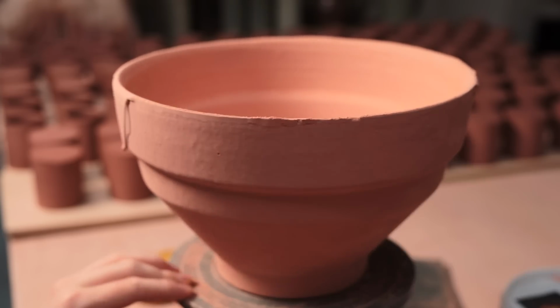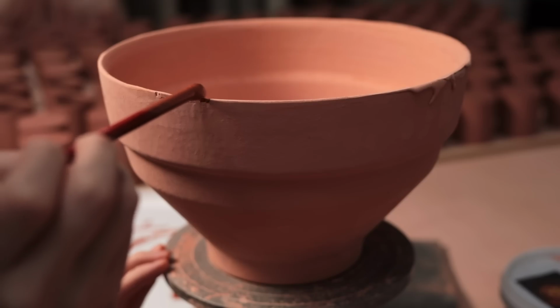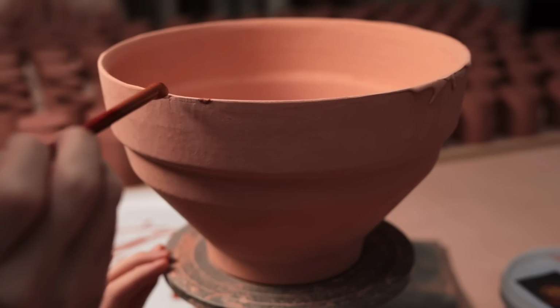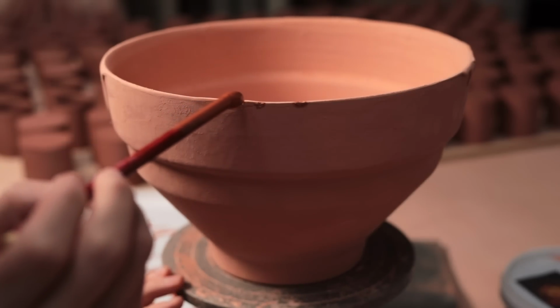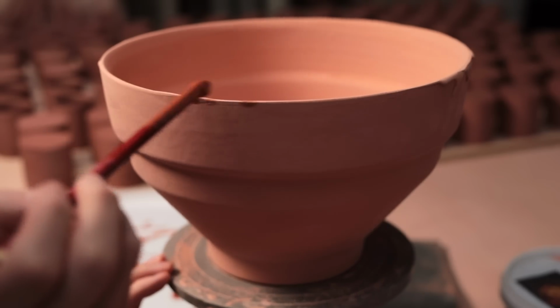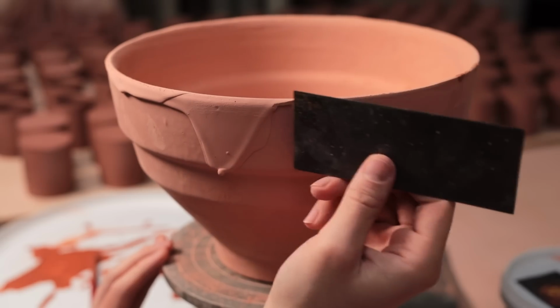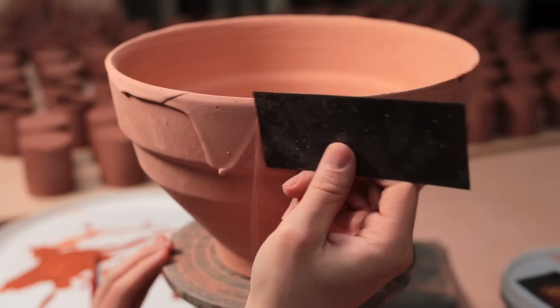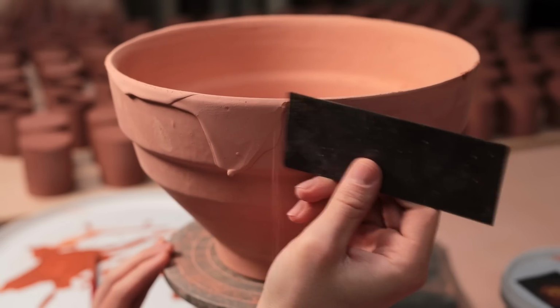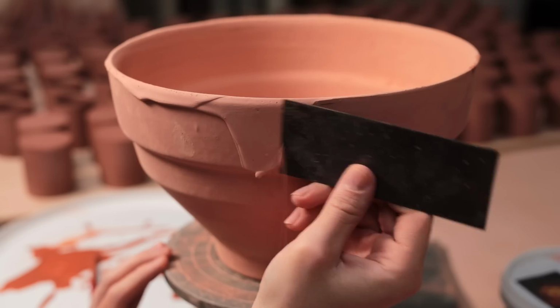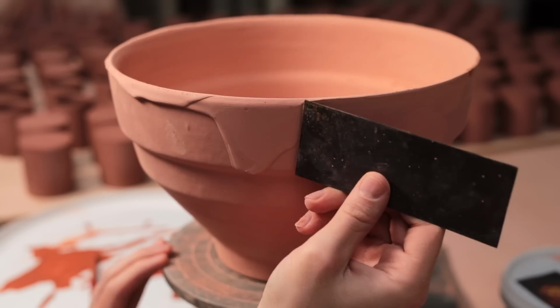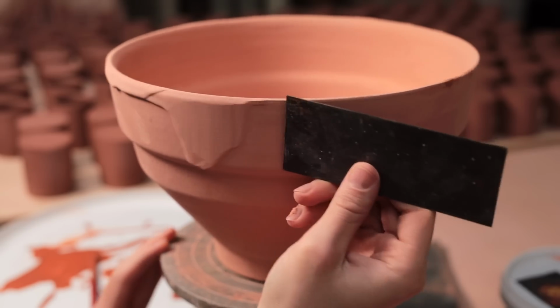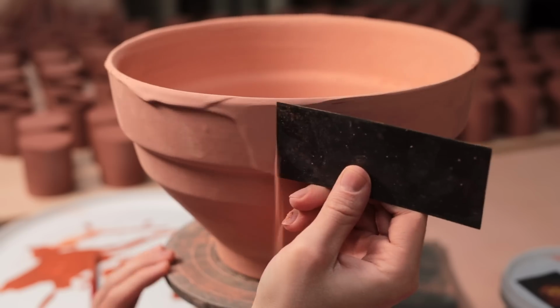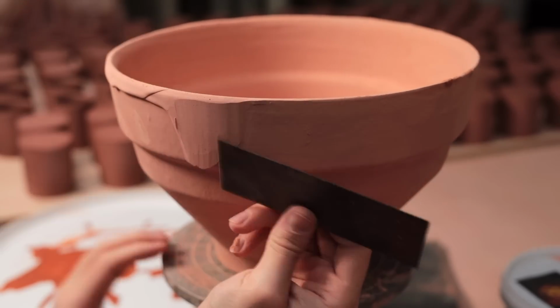I did have to dab some glaze onto a few areas where the glaze chipped off. In these cases, I tend to cover it with slightly more than need be, and then once it's dry, I rub back over these areas with a fingertip or the sharp metal edge and make it flush with the rest of the surface. It's worth mentioning though that fixing glazes like this does not work for every kind of glaze. Some will show these marks even if you fix them very carefully, whereas others, like this particular recipe, are quite forgiving and you can touch up areas like this if they've been damaged.